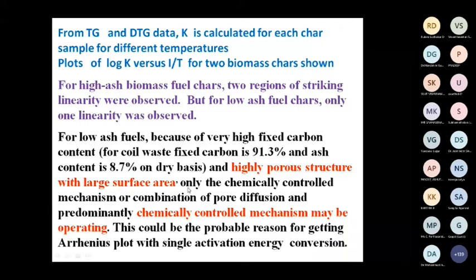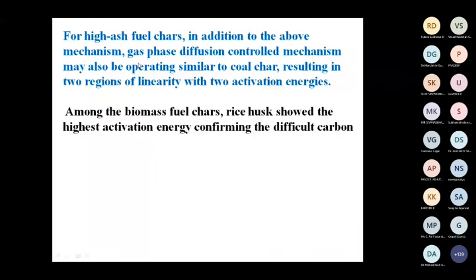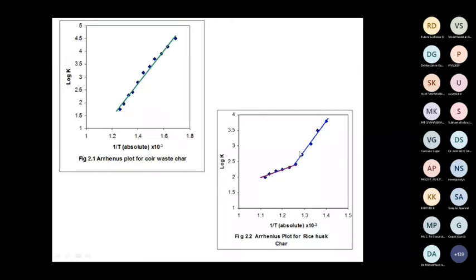Whereas for high ash char, in addition to the chemically controlled mechanism, because it is not highly porous, a gas phase diffusion control mechanism also may be operating. That is why we have two regions of linearity with two activation energies. So for high ash fuel we have two activation energies, and for low ash fuel we have one activation energy.